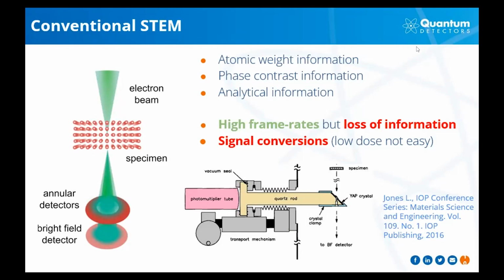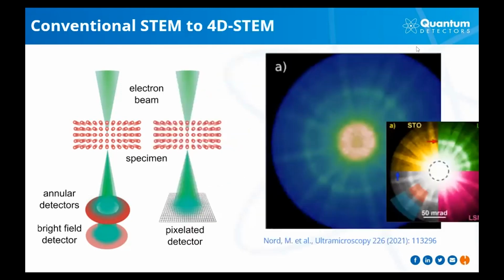Additionally, the established detectors convert the signal from electrons to light and photomultipliers, so basically there's a lot of additional noise added through the indirect detection, and therefore it's not as easy to work with them for low dose imaging. However, if we utilize a detector like MerlinEM, we can detect the full distribution of the electron beam. So this is a single example of a scan from a set of perovskite samples. There are different layers within the same specimen, just schematically shown here. But what it demonstrates is that there's a wealth of information which is not accessed.